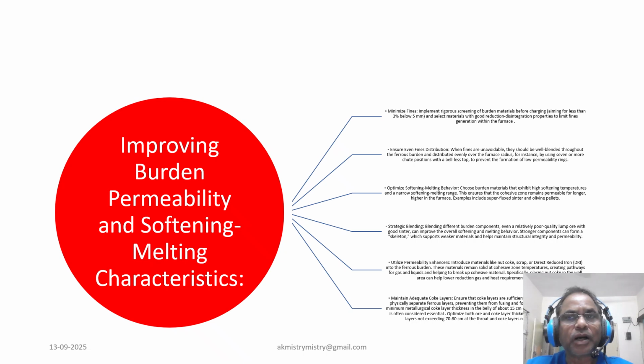Strategic blending is also highly effective. Even combining a relatively poor quality lump ore with a good sinter can improve the overall softening and melting behavior. The stronger components create a skeleton that supports weaker material, maintaining structural integrity and permeability. Furthermore, we can utilize a permeability enhancer or a spacer like nut coke, scrap, or DRI in the ferrous burden. This material remains solid at just above the cohesive zone temperature, creating a crucial pathway for gas and liquid and helping to break up the cohesive material. So placing nut coke, especially in the wall area, can help lower reduction gas and heat requirement in that region.